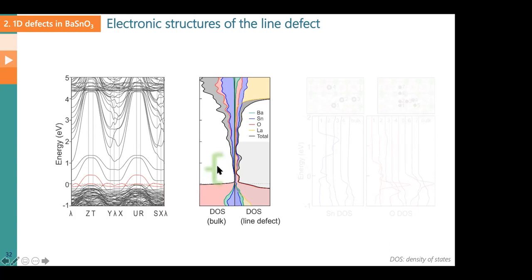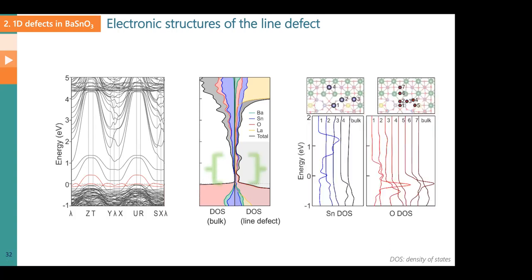So when we look at this band structure of the defect, what we realize is that these defects make the energy availability completely continuous. The defects create these red lines, red bands. If I don't have these red bands, I will have a gap. If I have a gap, electrons cannot conduct easily because there are energies they cannot take. That will dramatically reduce their mobility.